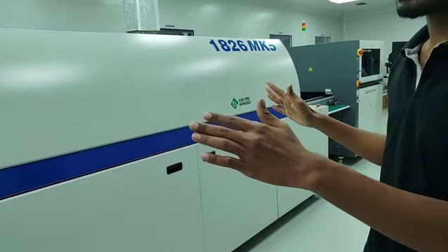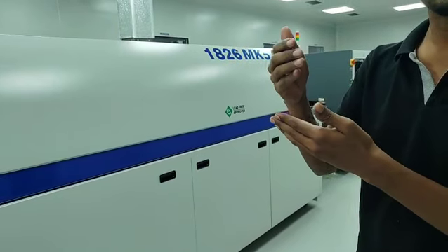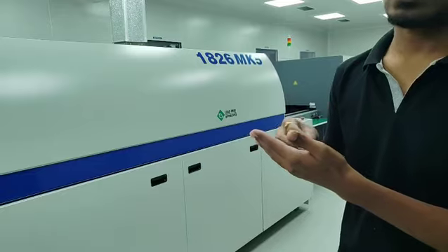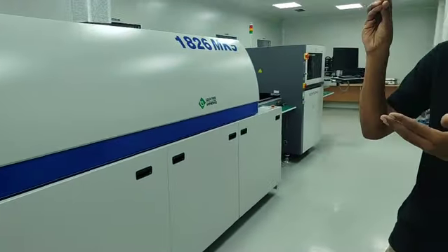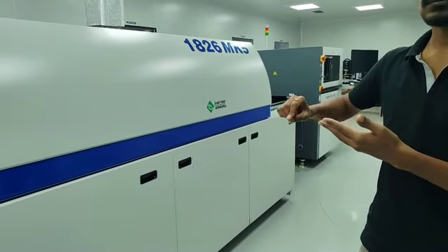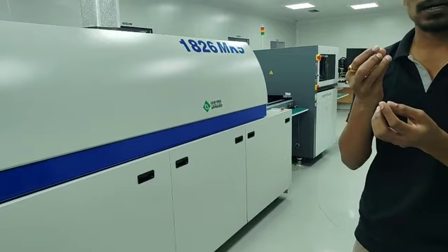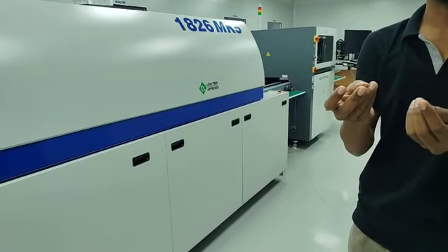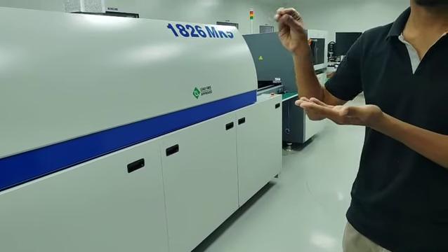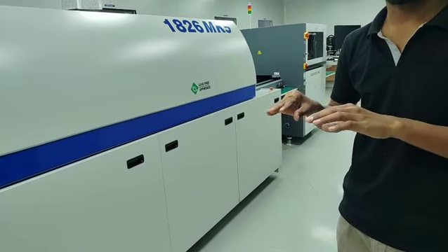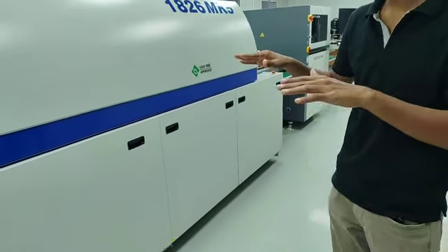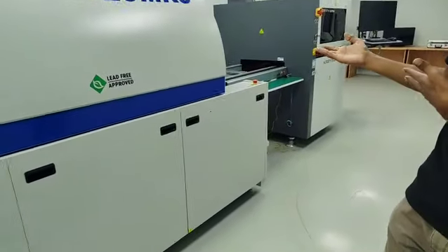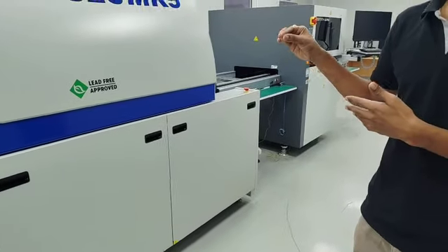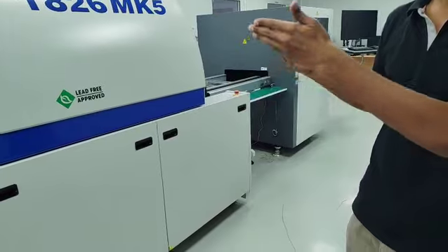Okay, sir. So there is the peak reflow. At the soaking zone, all the components have reached 180 degrees. Normally the melting point of the solder is 217 to 221 degrees centigrade. So the peak reflow is programmed to 230 degrees centigrade, so that whenever it reaches the maximum temperature, the solder particles, copper, silver and tin, start to melt. Once melted, the solder paste flows properly throughout the pad and the terminal. The last one is the cooling zone. Cooling does not mean a freezing temperature. It is just reducing the temperature to solidify the molten solder.